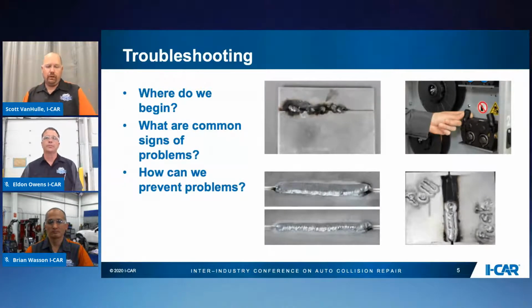So, Brian, on that lower left picture, what are we looking at there, and what is that weld puddle telling us? Oh, it looks like with that weld puddle, we've got too much voltage. Back when Eldon was talking about troubleshooting, once you verify that the software, the computer side of the welder, is fine, it's been factory reset, and you've told it what wire's in it, you're really down to hardware. And at that point, you're into the basics of welding. So it's always: is there a balance between voltage and wire speed? In that bottom left picture, if you look at the top weld, there's too much voltage and not enough wire speed. So why? Do I have the wire speed too high or too low? Is there some sort of setting that I'm not looking at?